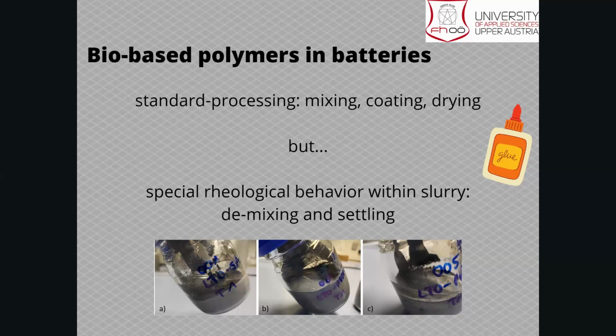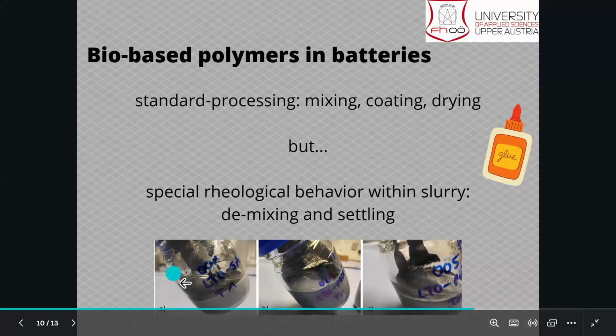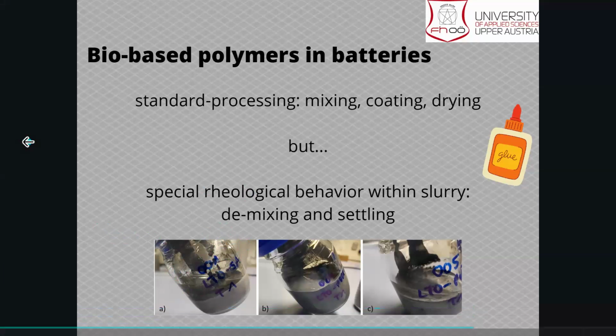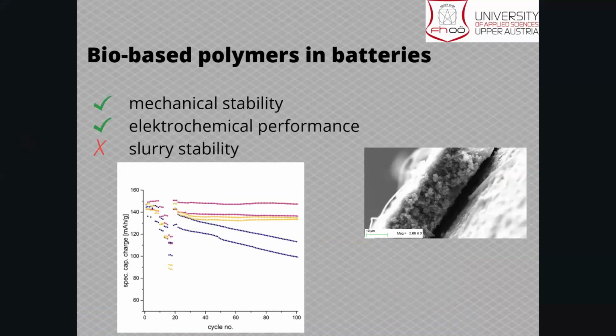With the standard binders, you just mix your slurry, which is then the mixture of all within the solvent. You can usually have it standing there for hours and nothing happens. If we are now talking about biopolymers, and especially about sodium alginate, you see that we do have a very, very high rate of demixing, especially you can see it on the very left side. That's of course not that advantageous. So it's also a time thing. You need to mix it, and suddenly after mixing you have to go on with the coating step, because otherwise it's settling and all your mixing step was for nothing. So this is something we had a closer look at.